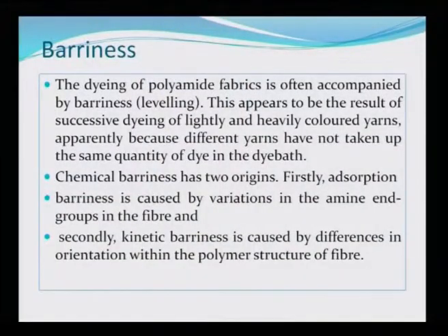Barriness. Let us learn this new term a little more in detail. The dyeing of polyamide fabric is often accompanied by barriness or unlevelness. This appears to be the result of successive dyeing of lightly and heavily colored yarns, apparently because different yarns have not taken up the same quantity of dye in the dye bath. Chemical barriness has two origins. Firstly, adsorption barriness is caused by variation in the amine end groups of the fiber, and secondly, kinetic barriness is caused by differences in orientation within the polymer structure of the fiber.